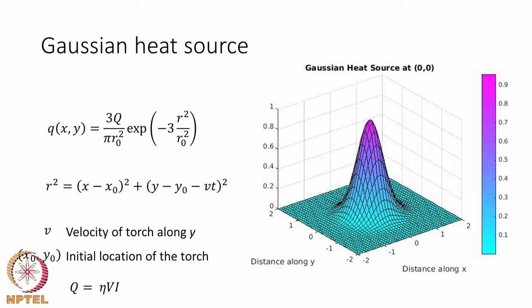and the distance variable r is written not just as a function of distance away from the origin of the heat source, which is at x naught and y naught, but also as a function of time. The reason being that the torch is moving, and as you can see from the expression written here, the radius is changing with the y distance as a function of time, which means that the torch is moving in the y direction. That is the meaning of the second expression we have given. X naught and y naught is the location of the heat source, which is at the center, and then the q value is nothing but the nominal heat source that is being given multiplied by the efficiency of the absorption of heat by the base material. So, eta V I, where V is the voltage and I is the current, that would be the power that is given, and that power is then distributed in a Gaussian manner.